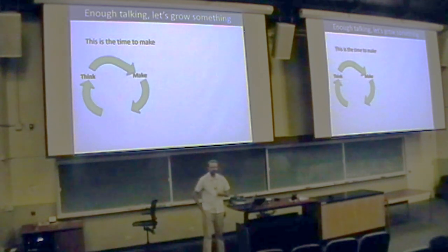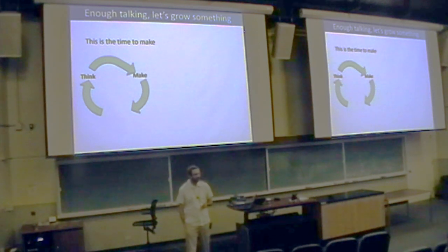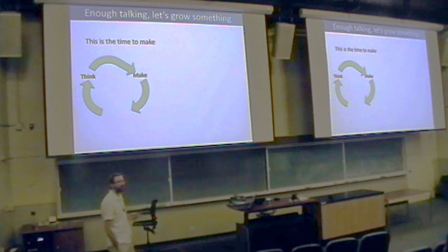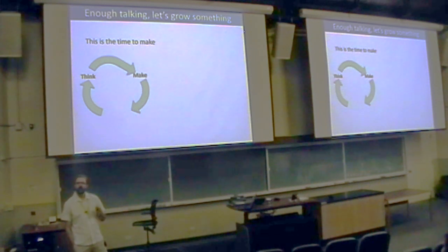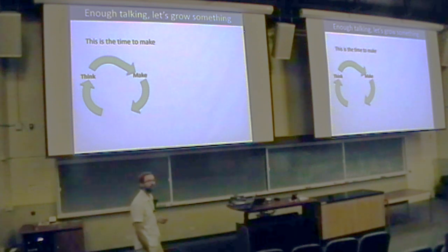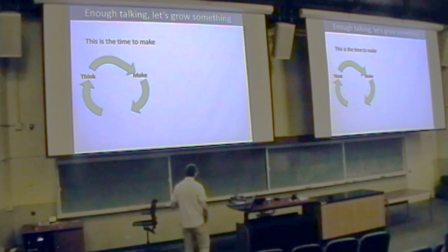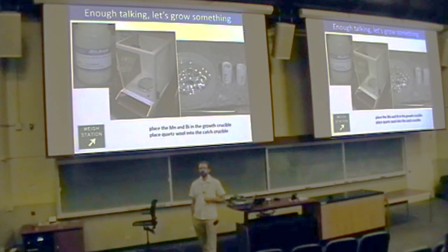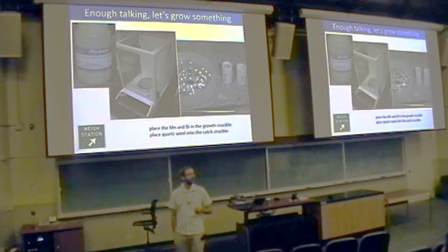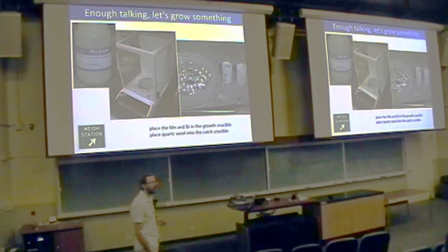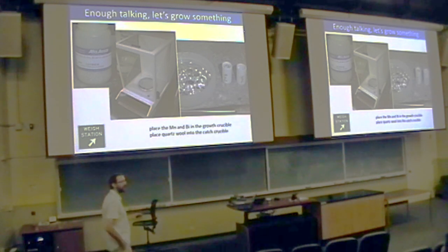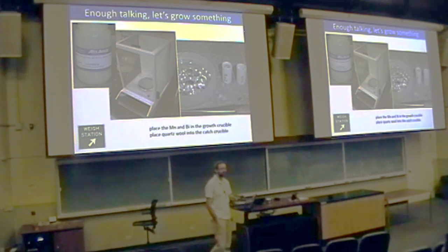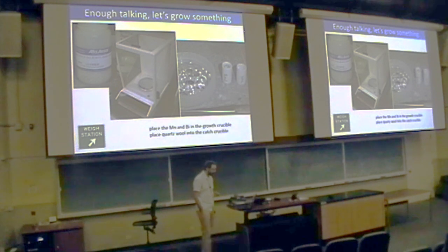Now that's in theory, right? That's all the concept I get from reading the phase diagram. But now I have my strategy. I'm an experimentalist. I want to go in the lab, and actually I want to do it, right? So what I'm going to start to do is take pieces of manganese, pieces of bismuth. I'm going to use a simple scale, weigh them to get the proper ratio. I want somewhere around 90% bismuth and 10% manganese.